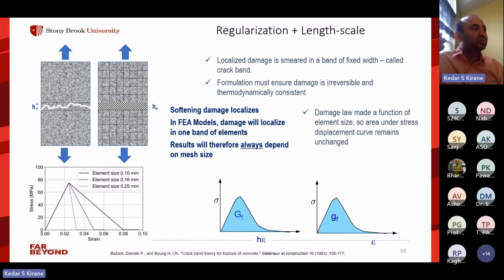Now, the simplest way to do that is actually make the energy dissipation per unit area a function of the element size. So if you look at this plot, stress versus strain at a single material element, single material point, this area is, let's say, small gf, which is energy dissipated per unit volume. We can relate it to the fracture energy of the material through a length scale h. Okay, so big Gf is actually h times small gf.